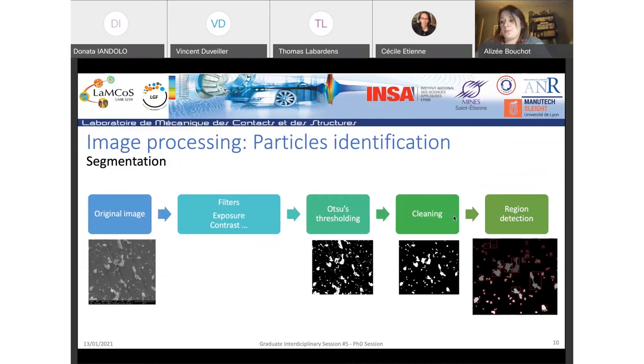The image is then cleaned up. This cleaning operation is done with different geodesic operations, like reconstruction by closing or opening. And finally, the regions corresponding to segmented particles are detected. You can see it in the red square on the image.